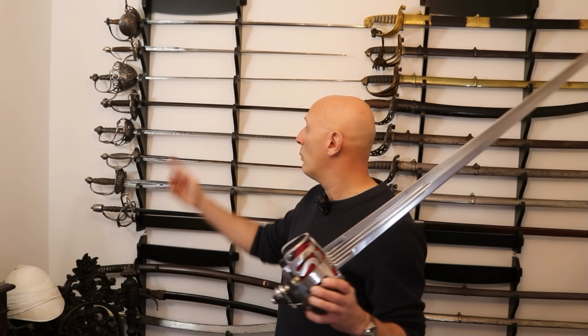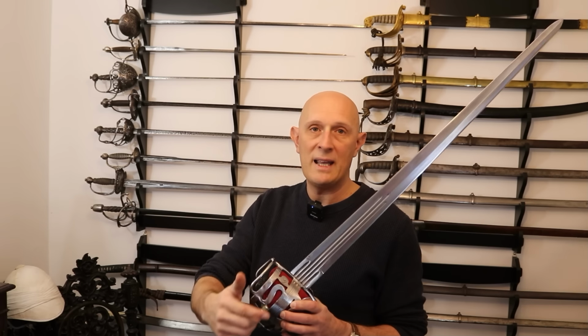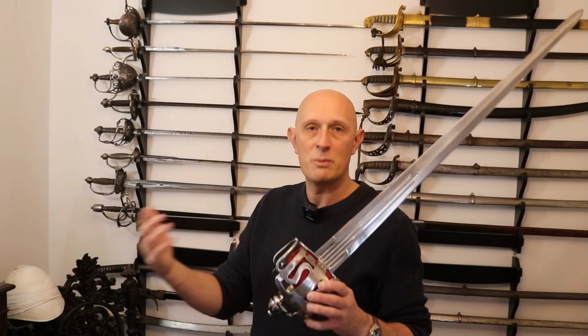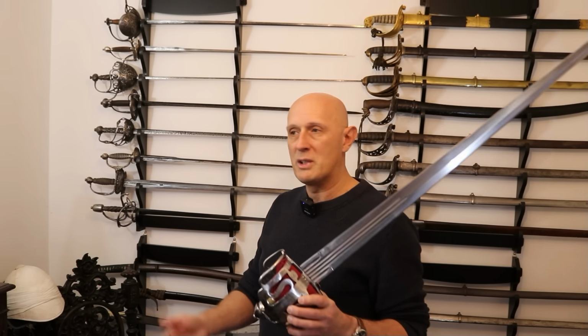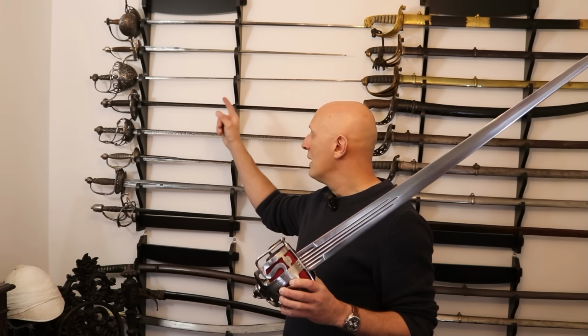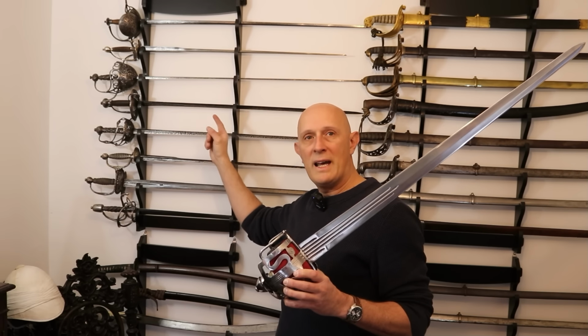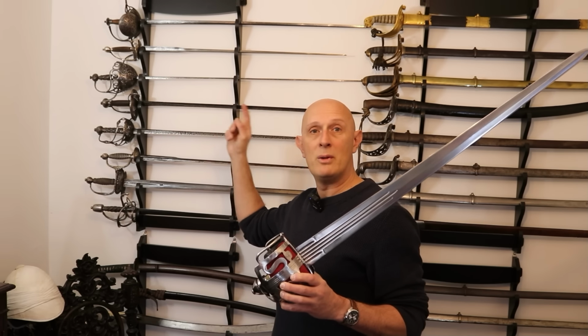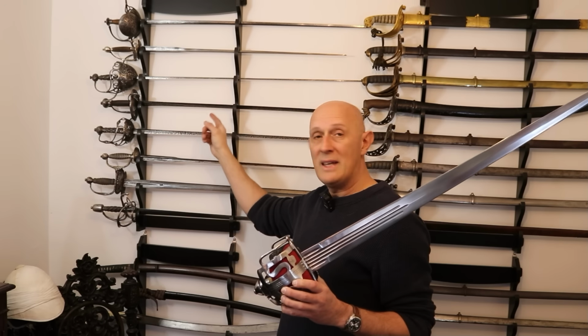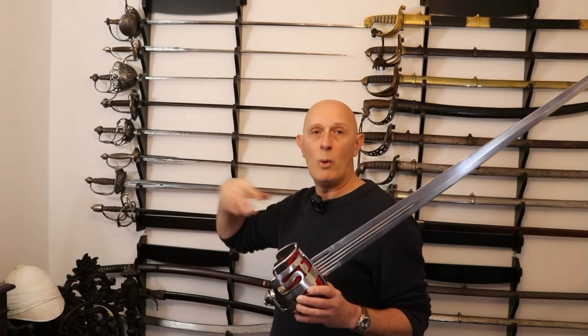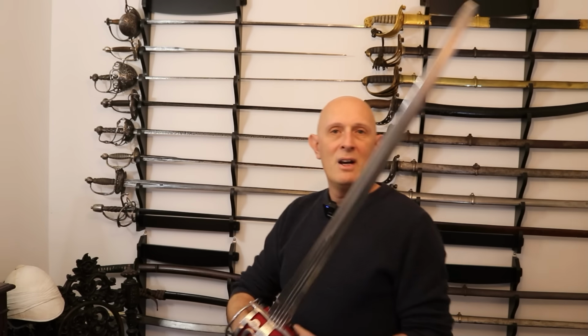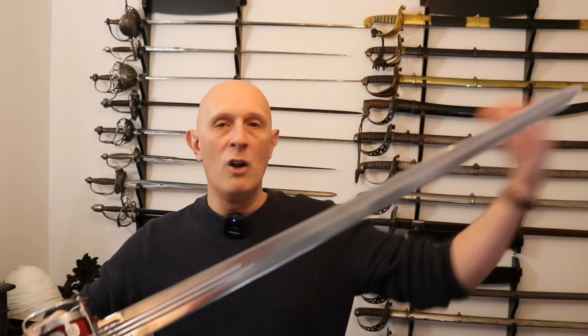And that's one reason why things like rapiers and small swords don't really appear very much outside of Europe, because Europe had this tradition of making springy blades. Now, not to say we don't find long springy blades in other places, we do, of course. There are long springy bladed Indian swords like the Urumi or the Firangi, and in Africa there's things like the Kaskara and the Takouba, which can be quite long as well. But fundamentally, the existence of rapiers with long, narrow blades goes hand in hand with having reliable, springy steel. You couldn't make these with hard edges and a soft body because they would just bend all the time because of their shape, essentially.